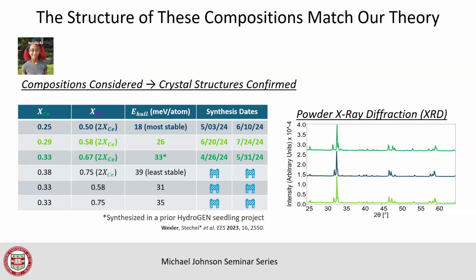So the first thing we'll characterize is, again, the structure. We'll shoot our X-rays at the material. The X-rays will bounce back. We'll process where they got shot. Hopefully they didn't hit us. And we will create a graph. Basically, that little theta there is an angle. So if you shoot the X-ray on the material, where does it bounce off? Measure the angle. By measuring the angle, you can reconstitute the structure. So here I'm color coding it: she measured this pattern of X-ray scattering off of a bunch of different materials. And if you compare those to our predictions of the structure, they match almost perfectly.